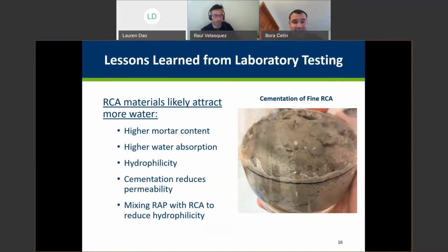On the other hand, the RAP-RCA mixtures or class 6 and class 5 aggregates had much lower hydrophilicity. Even some particles were hydrophobic because of the binder content. So if permeability becomes a concern, it is a really good idea to mix the RCAs with RAP for long-term performance. And cementation, again, in the picture here, water is being sucked in, and some of the cement particles are rehydrated, and even unhydrated cement left there starts being cemented, and it reduces some permeability of the material.